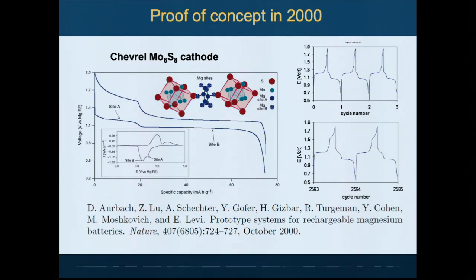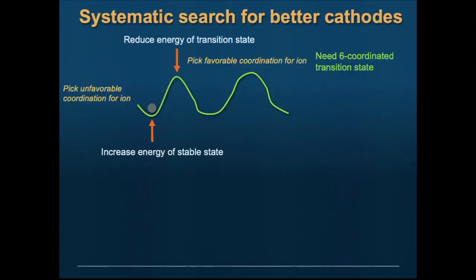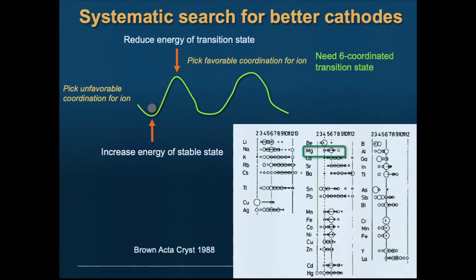The problem is that since 2000, we haven't exactly made a lot of progress. We made a little bit of progress, again, by thinking logically about the diffusion. And this is the story on which I'll end: the answer for making a good magnesium diffuser turned out to be remarkably simple. Again, if you think of this landscape, you want to get this down and this up. So if you want to move magnesium, you want the stable side to have unfavorable coordination, and you want the activated state to have more favorable coordination. If you look at the typical coordination environment for magnesium, it is mostly 6-fold. Magnesium is usually preferred as 6-fold, and occasionally goes 4-fold. So what do you want to make? You want a material where this is 4-fold and this is higher, like 6-fold.